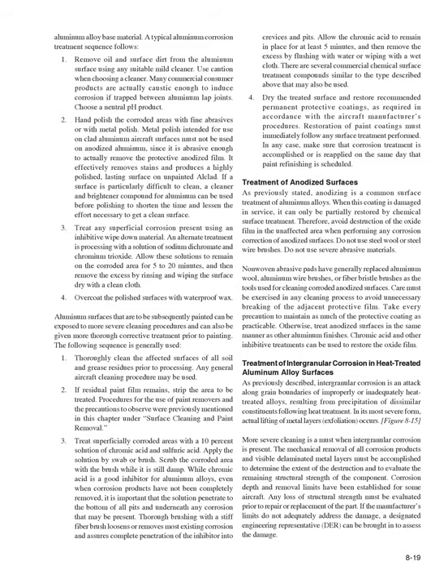Use caution when choosing a cleaner. Many commercial consumer products are actually caustic enough to induce corrosion if trapped between aluminum lap joints. Choose a neutral pH product. 2. Hand polish the corroded areas with fine abrasives or with metal polish.